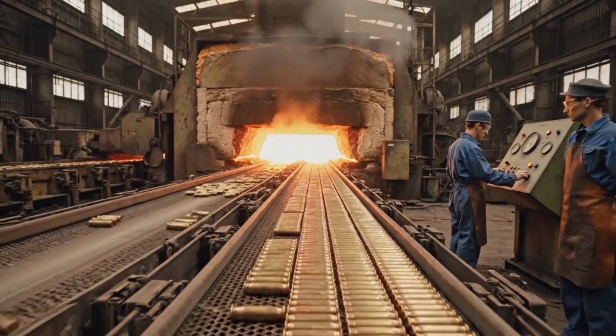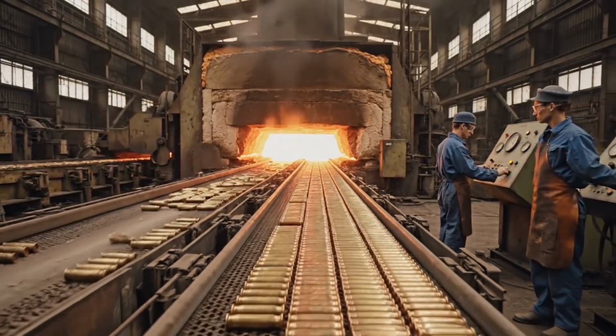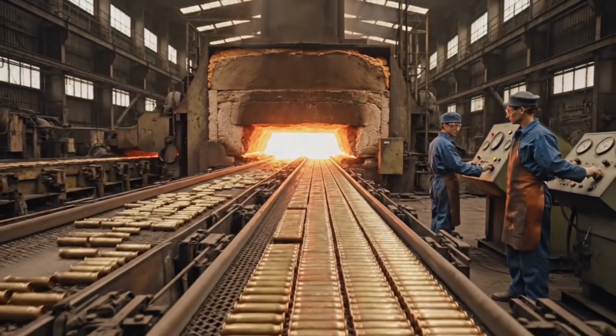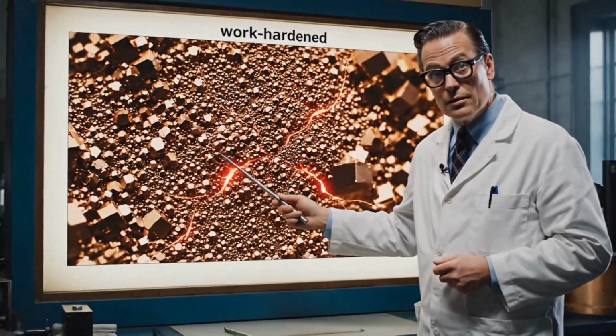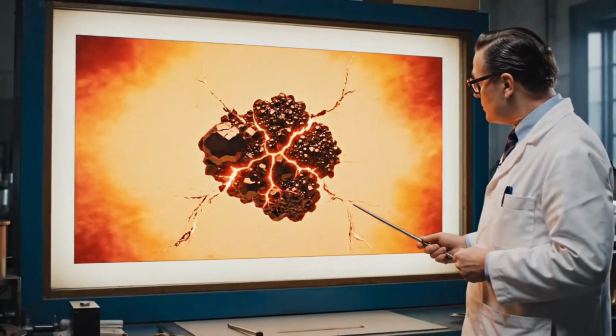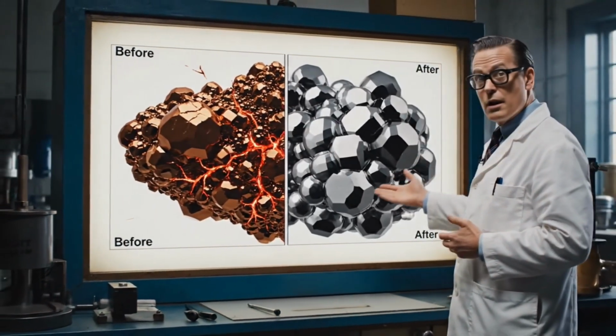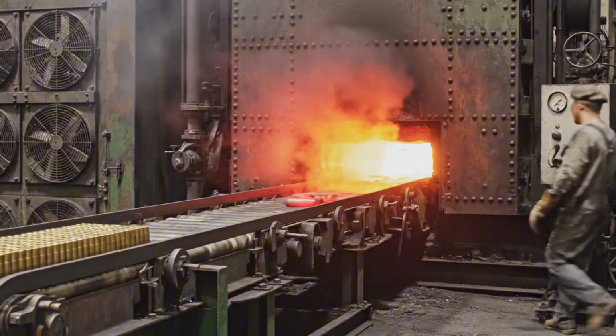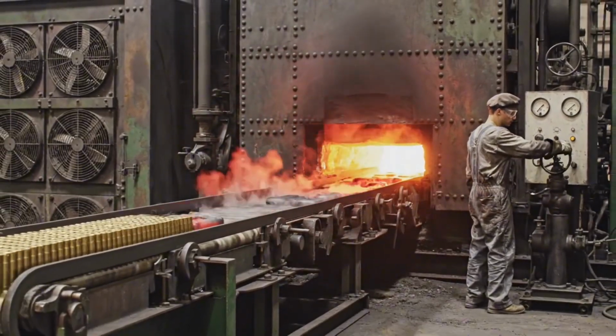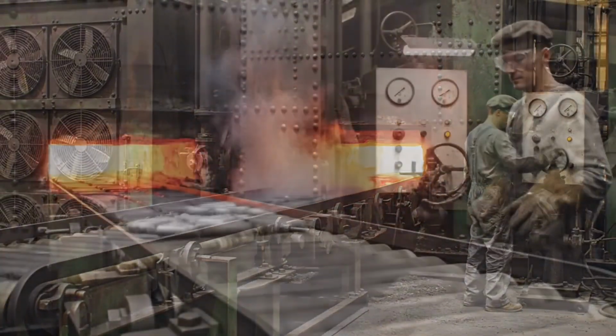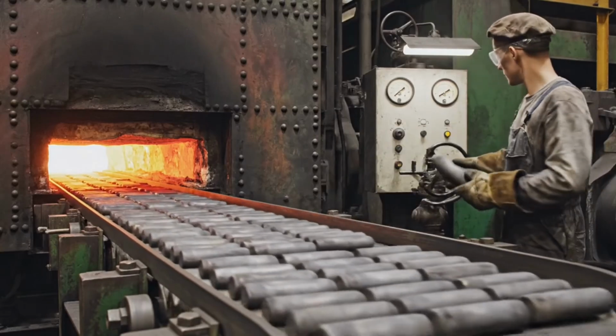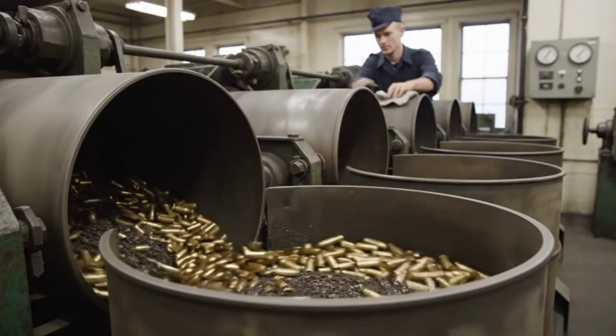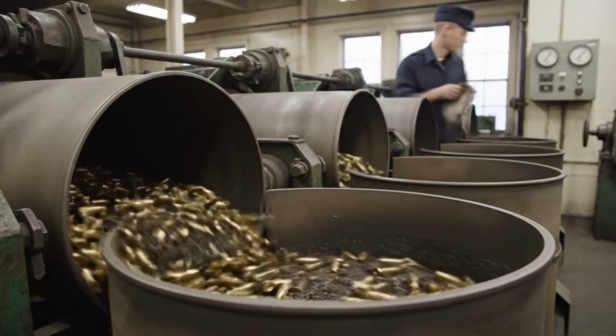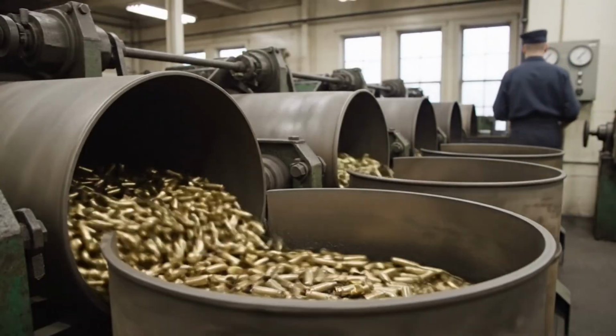Between drawing operations, the cases must be annealed again. The work hardening from drawing makes the copper brittle and prone to cracking. Annealing softens it so it can withstand the next drawing operation. The cases travel through long furnaces on conveyor belts, heated to precise temperatures, then cooled. After annealing, they're cleaned in tumbling barrels filled with an abrasive media that polishes away any scale or discoloration.